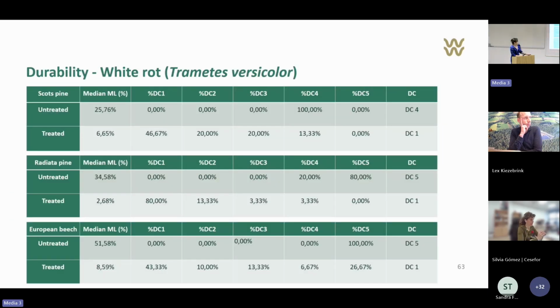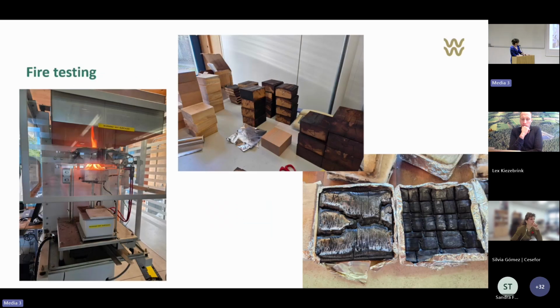Here you can see the results of the white rot test with Scots pine, radiata pine, and European beech. All of those achieved durability class 1, which is really nice and a significant improvement. We also ran durability tests for other materials, but here we focus on the wood modification.